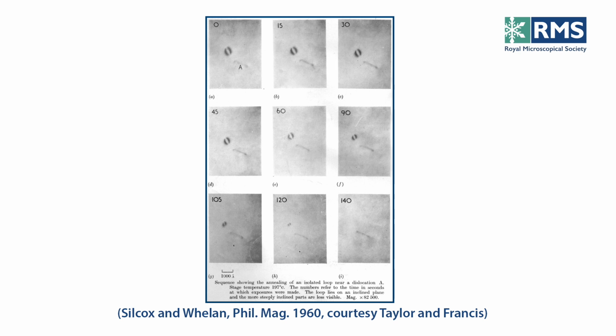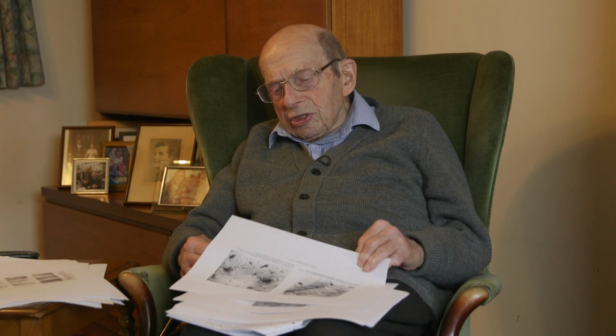And from the rate at which this happens, you can determine the activation energy of this process, which is in fact diffusion. This shows that the electron microscope can be used not only to show pretty pictures, but in fact also as a lab, to do experiments on.